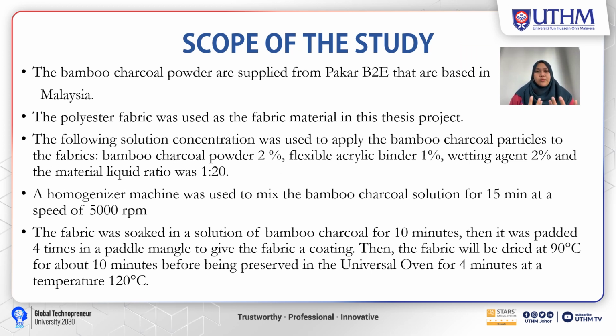Okay, the bamboo charcoal powder is supplied from Pakar B2E that is based in Malaysia. The polyester fabric was used as the fabric material in this thesis project. The following solution concentration was used to apply the bamboo charcoal particles to the fabrics: bamboo charcoal 2%, flexible acrylic binder 1%, wetting agent 2%, and the material liquid ratio was 1:20. A homogenizer machine was used to mix the bamboo charcoal solution for 15 minutes at a speed of 5000 rpm.